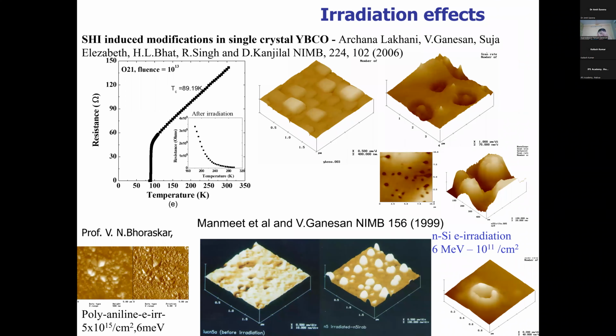See, this is one of the very first experiments we did long back. We had a superconductor. We irradiated it with high energy ions from the Nuclear Science Centre, Delhi. Why do we irradiate it? We want to create a defect. Why create a defect? Otherwise a pure superconductor is useless. If you put in a defect, then its current carrying capacity, the critical current density, increases. That is why we did it.